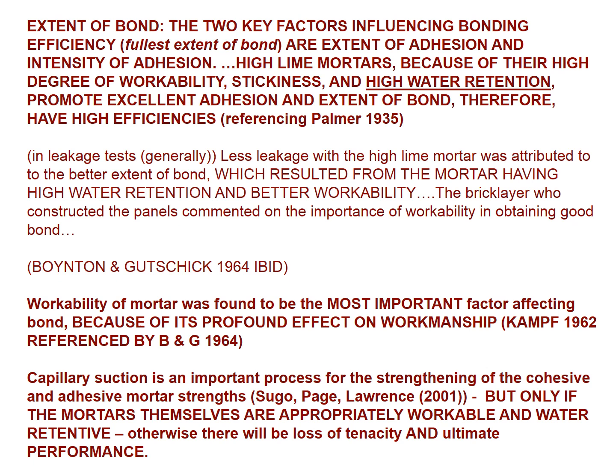In leakage tests carried out by Palmer, less leakage with the high lime mortars was attributed to the better extent of bond, which resulted from the mortar having high water retention and better workability. The bricklayer who constructed the panels commented on the importance of workability in obtaining good bond. Workability was found to be the most important factor affecting bond because of its profound effect on workmanship.